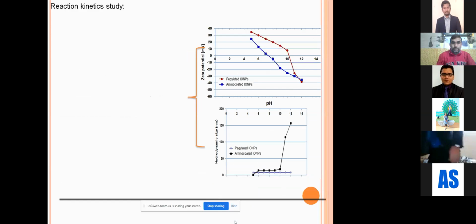So when you have prepared the nanoparticle, the reaction kinetics is very important. Why? Because I told you the nanoparticle has to be reactive, has to be dispersed onto the surface. It should not get agglomerated or aggregated inside the system where you want to target. So what we have done, we have tried checking the effect of temperature and pH, whether the reaction kinetics of these prepared pegylated or amino coated iron oxide nanoparticles has changed drastically or not.